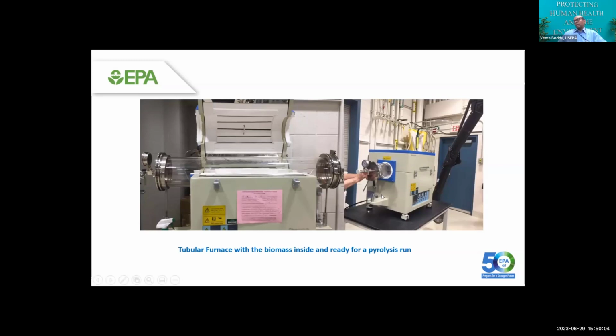As previously mentioned, within a short time we used only 500 and 700 degrees. We wanted to avoid the torrefaction temperatures of 200 to 300 degrees Celsius. Our heating rates are about 10 degrees Celsius per minute.